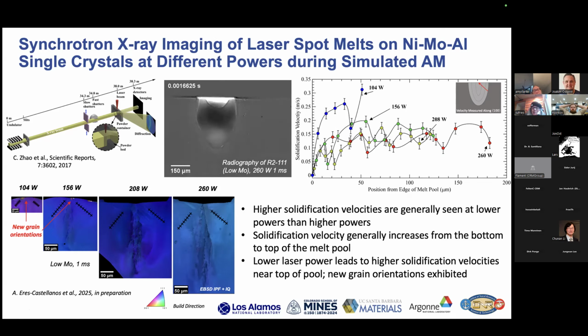We can then couple this with postmortem characterization. So this is an example of polishing into the midplane of these samples. And you can see for the high power conditions and doing crystallographic mapping, we're able to retain the substrate orientation, which is actually pretty neat if you're interested in things like repair scenarios of single crystals, as an example.